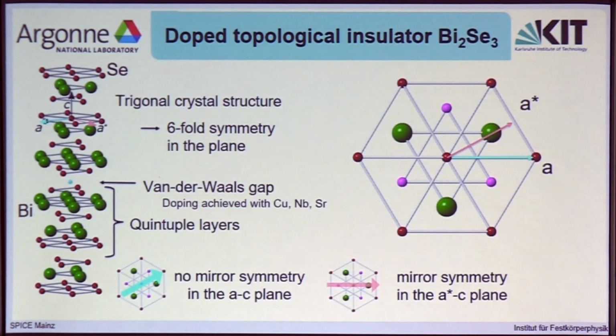Let me quickly introduce this compound to you. Bismuth selenide has a trigonal crystal structure, which naturally leads to a six-fold symmetry in the crystal plane. It's composed of quintuple layers of bismuth and selenium stacked on top of each other, and those layers are separated only by a weak van der Waals gap, making it easy to intercalate doping ions. And as I have said in the beginning, the doping that we will be looking at will be done by copper, niobium, or strontium.